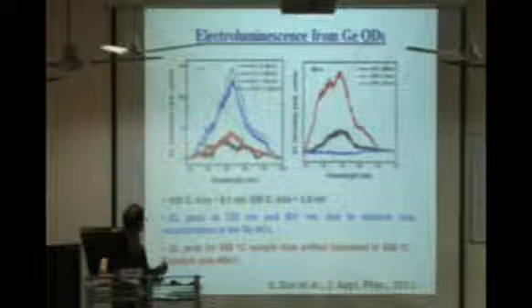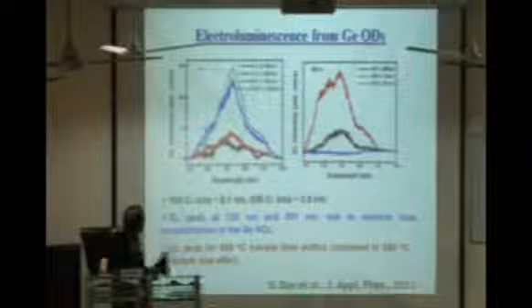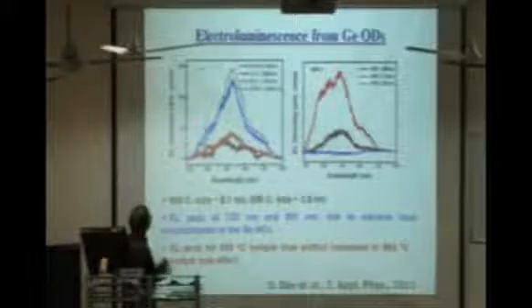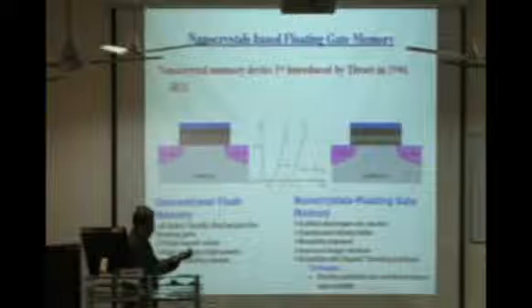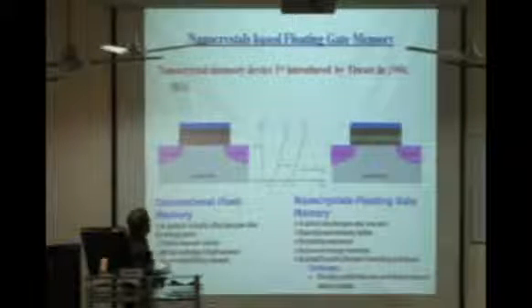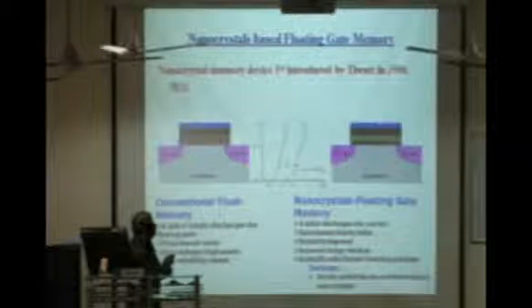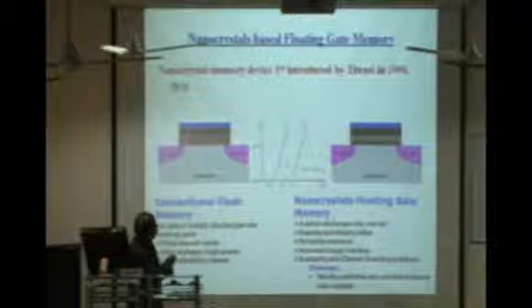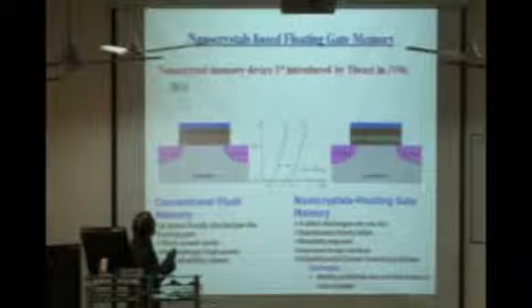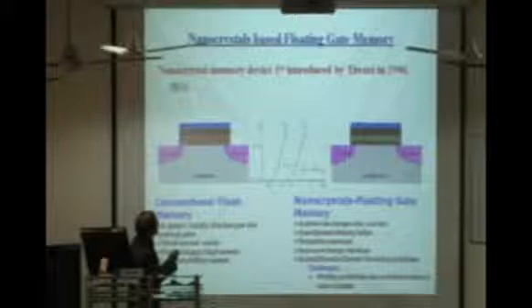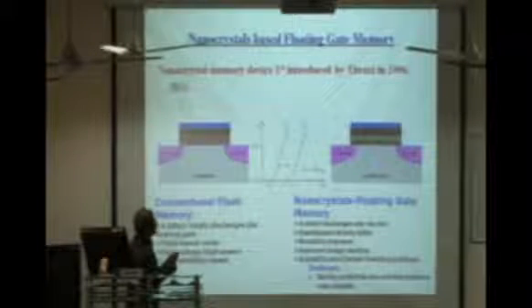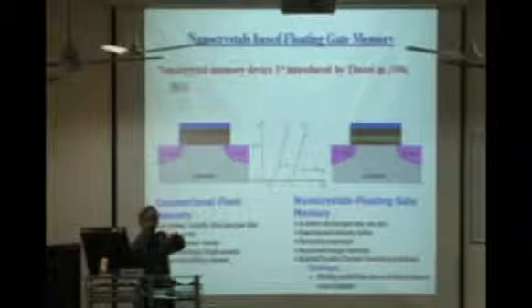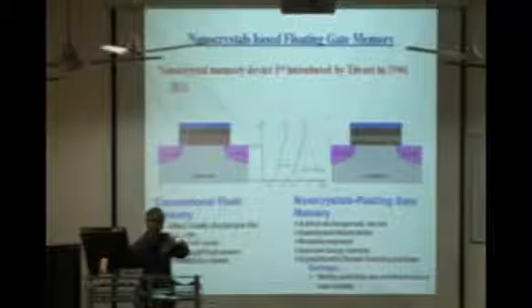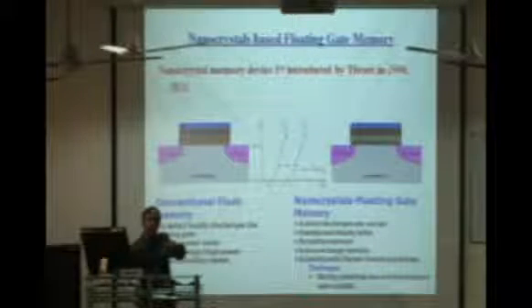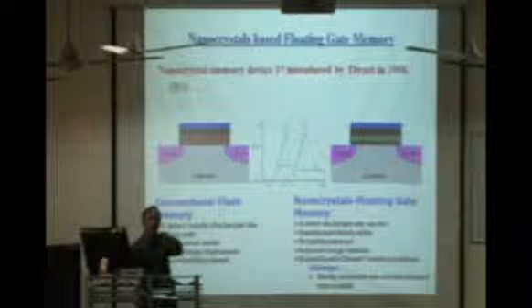So this works better. And this electroluminescence peak is almost in agreement with the photoluminescence peaks that you see over here. And probably the last 2 slides or so: as I said, these quantum dots, if they are embedded and isolated, in fact, this was one of the first demonstrated at IBM by 1996 by Sandip Tiwari, that these quantum dots can be used as charge trapping nodes, and if they can be used as charge trapping nodes, they can be used as a memory.